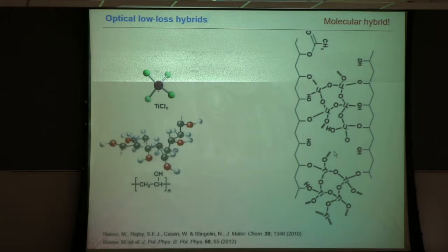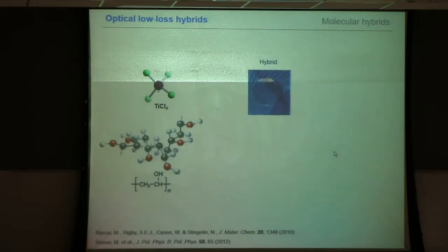Why is that so important? We try not to form particles, but we try to actually make epoxy where we cross-link the polyvinyl alcohol with the titanium oxide, titanium polymer, or vice versa, depending on the amount you have. And you see it works beautifully already when you make a picture of a film of the hybrid. It's very difficult to see.